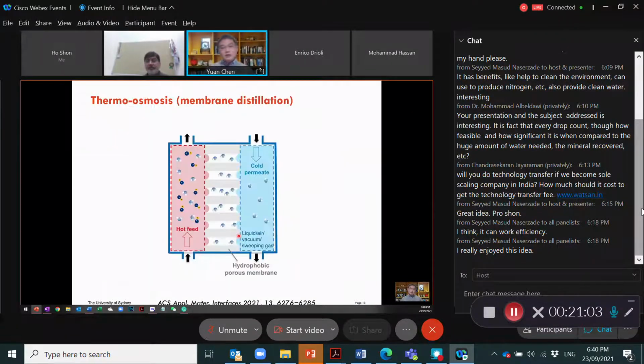Then step two is, since we already have the heated source solution, we can also integrate that into a membrane desalination process. I think most of the membrane experts know about this in detail. So if you put this hot solution here, then the water moisture will go through and condense on the other side. Which means if we couple this thermal osmosis process with a lithium extraction process, using a heated source solution, we will be able to generate fresh water. At the same time, we can also continuously concentrate the source solution during the whole extraction process.